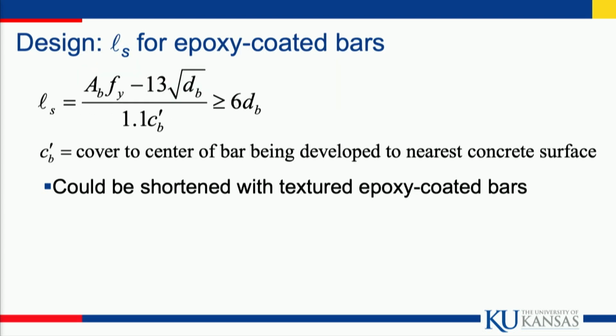What does design look like? Design looks different from what you have in regular AASHTO for uncoated bars. Splice length, and in this case, the product of the area of the bar times the yield strength, minus, this is for the epoxy-coated bars, minus best fit, this is 13 times the square root of the bar diameter divided by 1.1, where CB prime is the cover to the center of the bar to the nearest concrete surface. This can be shortened if we went with the texture-coated bars.